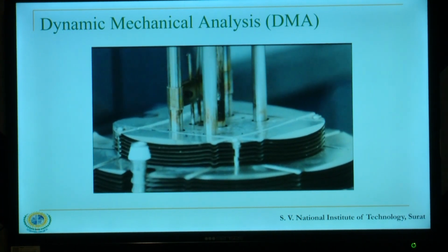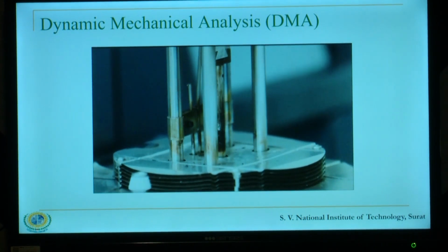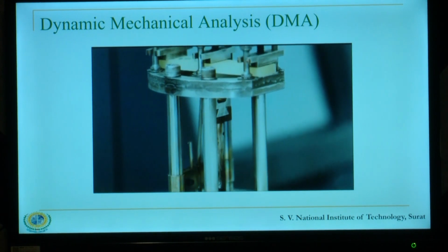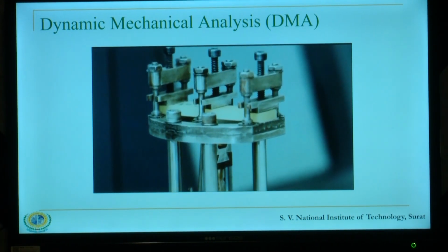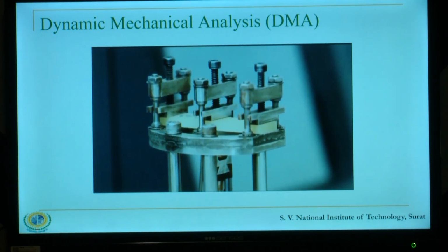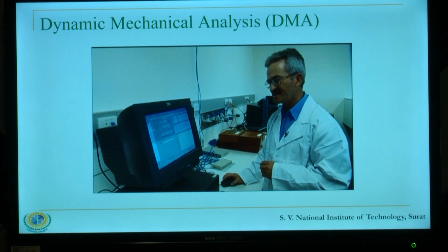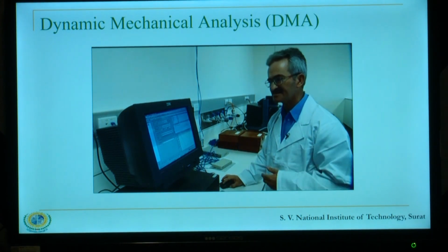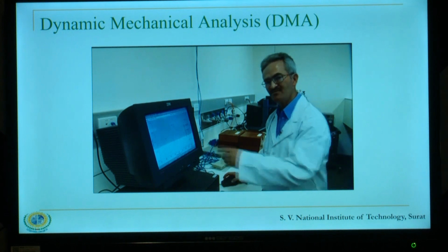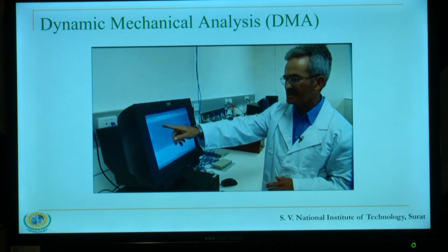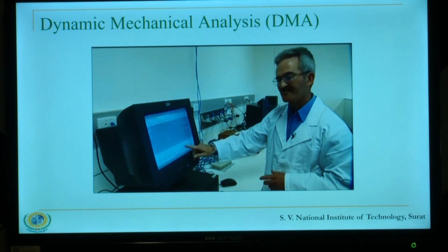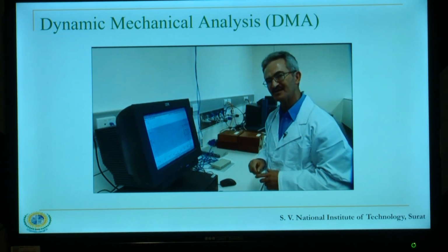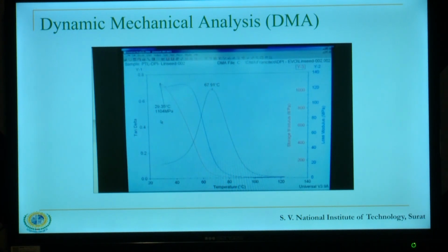The DMA applies force sinusoidally at several frequencies over a temperature range. As the sample deforms, displacement is automatically measured. The magnitude of the applied stress and the resultant strain are used to calculate the stiffness of the material under stress. Once all the parameters have been set up for the DMA analysis, the test is run, and at the end you will end up with different values for the samples, such as the storage modulus and loss modulus. The storage modulus is the measure of the sample's elastic behavior, while the loss modulus is the measure of the sample's viscous behavior. The ratio of the loss to the storage is the tan delta.